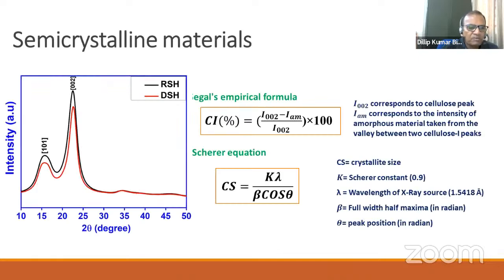And this is a semi-crystalline material. I told you about the polymers. Polymers all have both crystalline as well as amorphous phases. The peaks correspond to the crystalline phases, and the rest is the amorphous part. From there, you can identify the crystallinity index with Segal's formula, and the Scherrer formula will tell you the crystallite size.